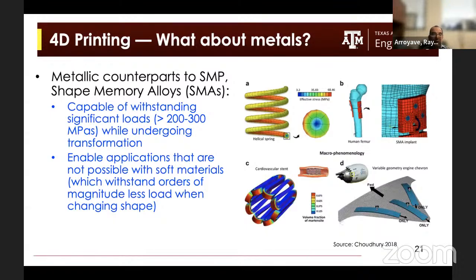So for example, if you want actuation at high temperatures, you're probably not going to be able to do it with shape memory polymers. And there are examples of shape memory alloys, including a lot of alloys discovered at Texas A&M by Professor Karaman, for example, that can undergo these reversible phase transformations at temperatures as high as 800 degrees Celsius, right? So clearly, as soon as you reach temperatures of 200 and above, having to carry loads that are hundreds of megapascals, these are operating conditions that soft shape memory polymers cannot sustain, right? So there is clearly an opportunity to try to do something related to 4D printing with shape memory alloys.